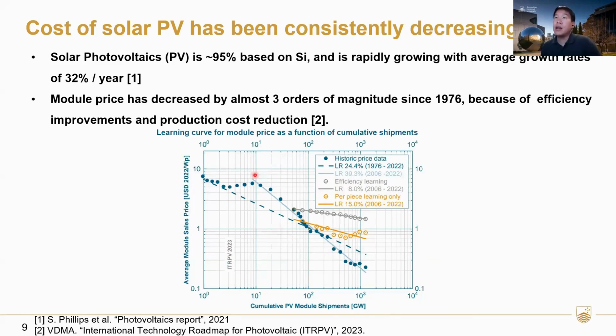And the breakdown of the cost improvement can be attributed to two main components. So that's the one in gray, efficiency learning, contributing about 8%, and the per piece learning, that's a production cost reduction of about 15%. Combined, it means that every doubling of the cumulative shipment, the price reduces by about 25%. So what this graph highlights is that if you want to further decrease the cost of PV, and there are a lot of incentives to do so, to make it cheaper and more widespread, we need to consider not only the efficiency of the devices, but also the production cost of it.